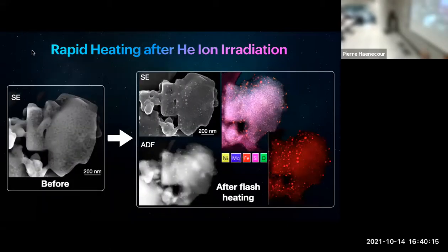Showing you in a larger field what happened to the sample. It's basically a lot of bubbles all around it, and then released afterwards. You can see that now it's mostly composed of those iron nickel particles. They are literally everywhere after heating at 1,000 degrees for several minutes. So in just a single olivine grain, you basically locally accumulated iron to form iron metal within the silicate.